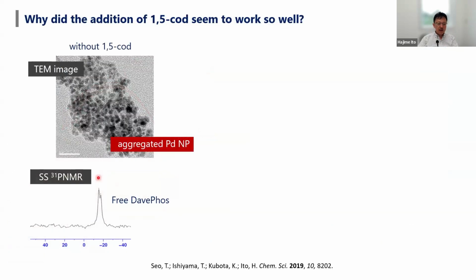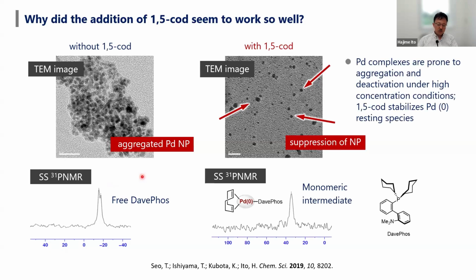This slide shows why addition of 1,5-COD improves this reaction. This is a TEM image after reactions in the absence of 1,5-COD. You see palladium can aggregate with each other to form palladium nanoparticles, so-called palladium black. This palladium black has very low activity for cross-coupling reactions. In the solid state NMR, we see free phosphine was generated, meaning the palladium phosphine catalyst decomposed under the ball milling reaction conditions.